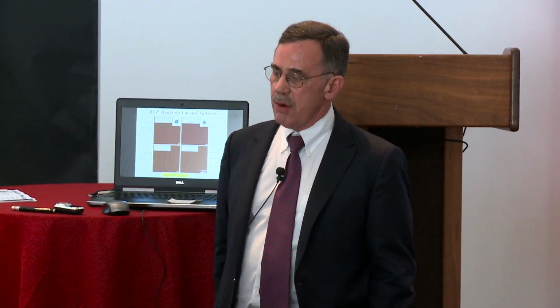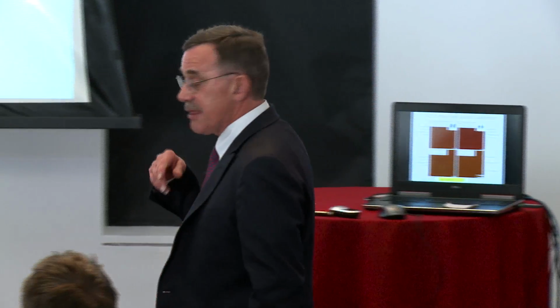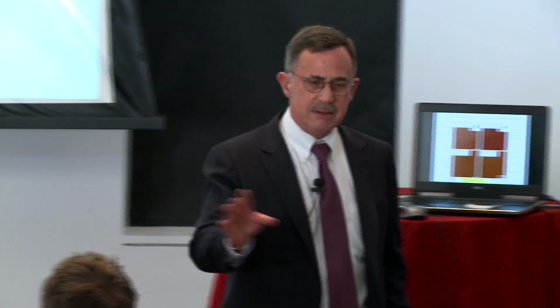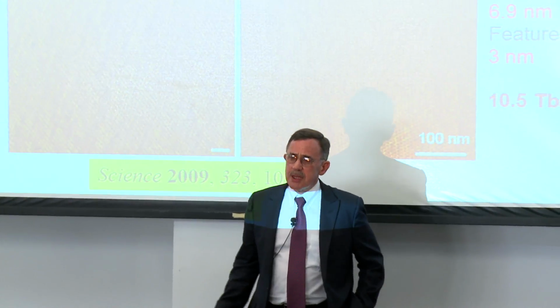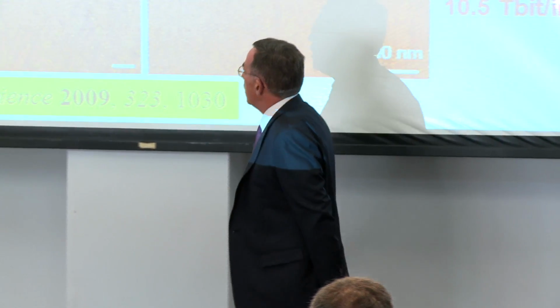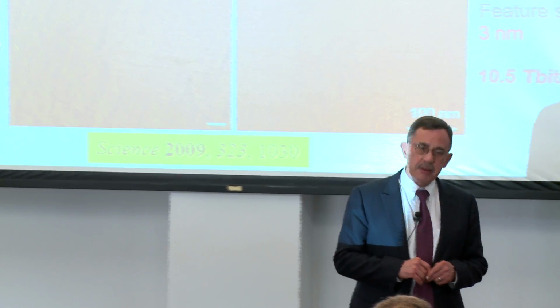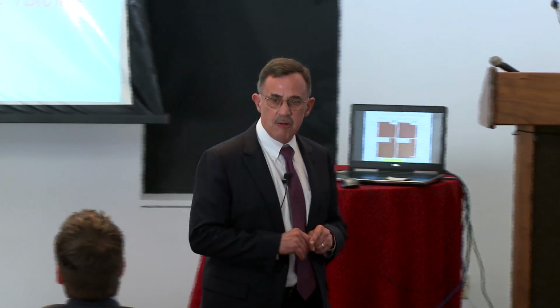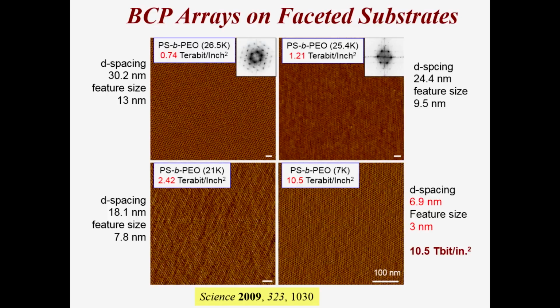Now, are we perfect? I can increase the lateral order quite well. And in fact, this happens to be styrene ethylene oxide, again, red and blue. So Jenny, don't worry. You don't have to worry about what polyethylene oxide is and polyvinyl pyridine. You just think poly red and poly blue. Okay? So now here we can change the molecular weight. And if we change the molecular weight, the size scale of the structures gets smaller. And they get smaller, and they get smaller. In fact, we can generate these structures with a pitch with polystyrene polyvinyl pyridine of about 6 nanometers. That's 10 terabit per square inch. That translates to roughly about 30 DVDs on a quarter.